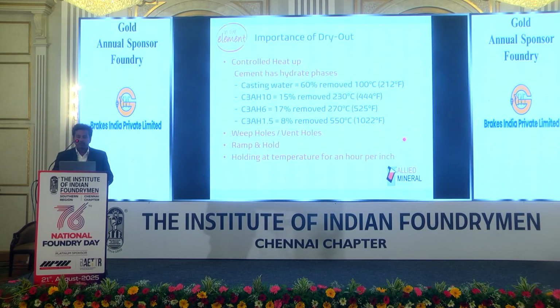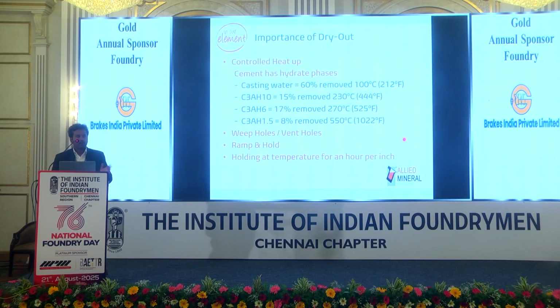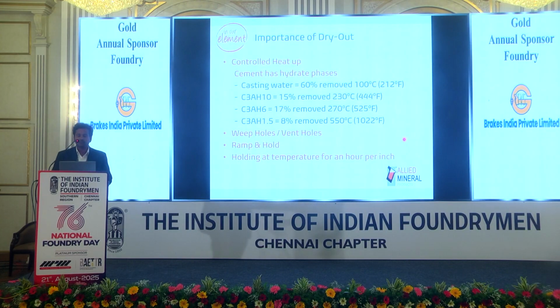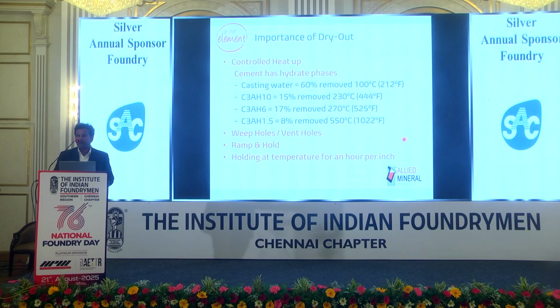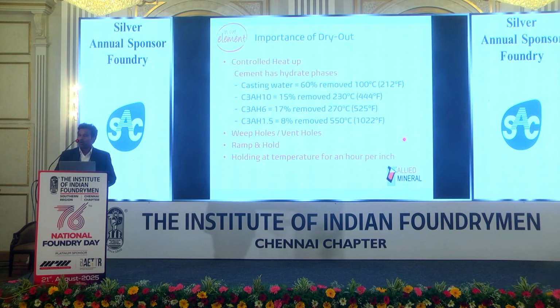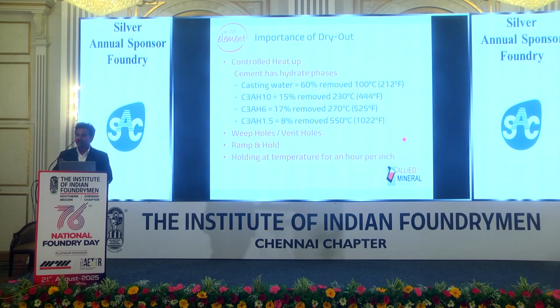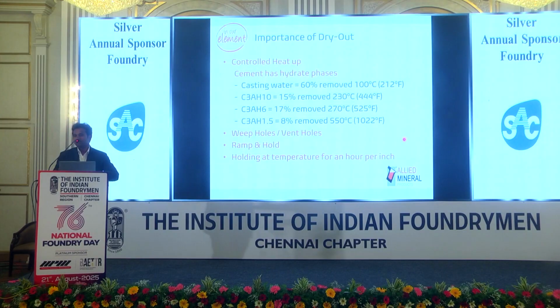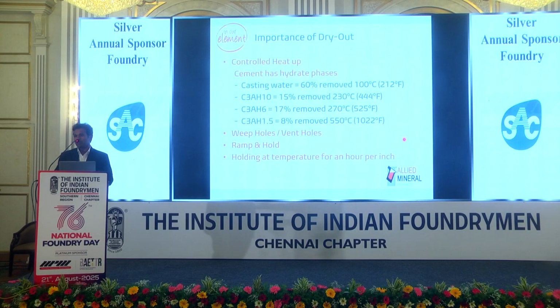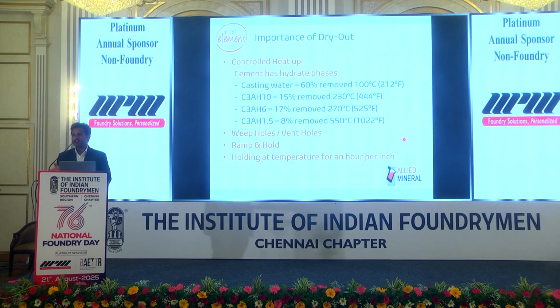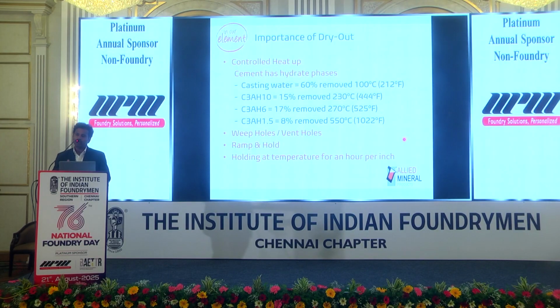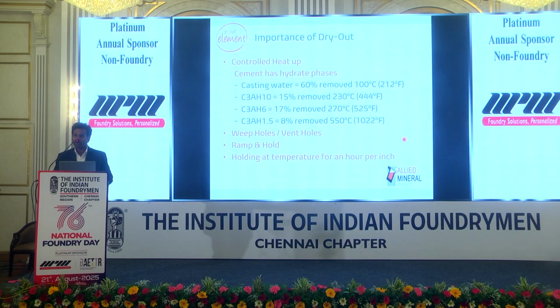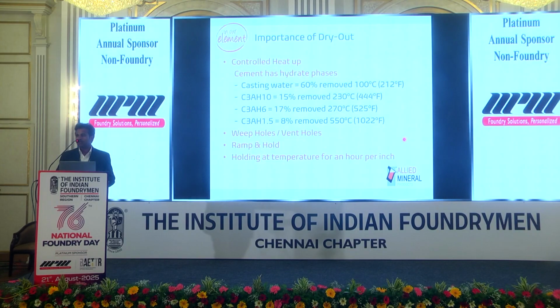When you look at the calcium aluminate cement based castable system, one major part is the dry out. Whatever water we add has to be removed without damaging the refractory system. The physical water we add, 6 to 7% in a low cement system, will come out around 100 degrees Celsius as water vapor. But it is not the same.